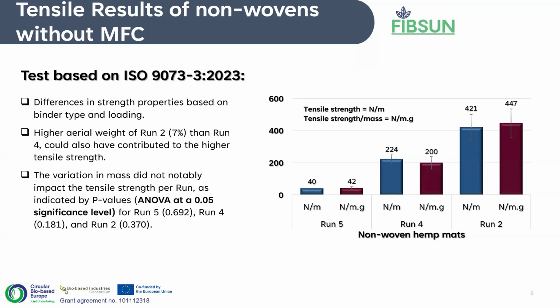what we did again is we realized that regardless of the fact that we already understand the area weight of the nonwoven as per what was delivered, due to the way this test was performed, it was imperative to understand the impact of the weight of the nonwoven on the tensile properties. The reason being, we noticed variation across the nonwoven rolls in terms of the area weight. So we wanted to also normalize the tensile properties. From the base nonwoven material, we could see that while there is variation, it's not anything notable in the area weight of the nonwovens.